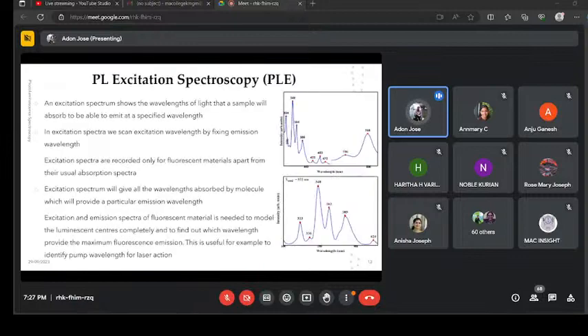So here starts with PL excitation spectroscopy. Actually, the primary criterion for obtaining the correct luminescence spectra of a sample, or the actual luminescence spectra of the sample, is to record it with the proper excitation wavelength. That means if we want to record the absolute luminescence spectra of a material, the first factor that we need to know is the excitation wavelength. This can only be identified from the excitation spectra. So for recording the luminescence spectra, we need the excitation spectra.